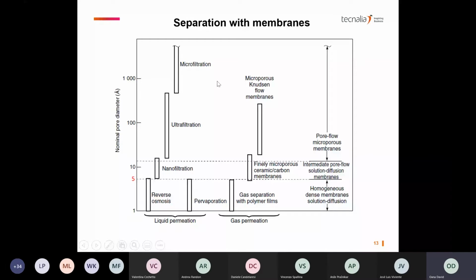If we look at liquid filtration, we have ultrafiltration and microfiltration. And if we look at gas separation, we have some kind of Knudsen flow membranes, which are not very selective but have high fluxes. And then all polymer membranes that separate gases are dense. In between 5 to 20 angstrom, we have an intermediate domain. The membranes are neither dense nor porous. From the gas separation point of view, this is a highly interesting domain because here the membranes are able to separate according to the size of the gases. So they have a sieving mechanism. There are different types of materials that can do that. It can be carbon-based, ceramic-based, or mixed, like a hybrid between metal and organic molecules, which are metal organic frameworks.